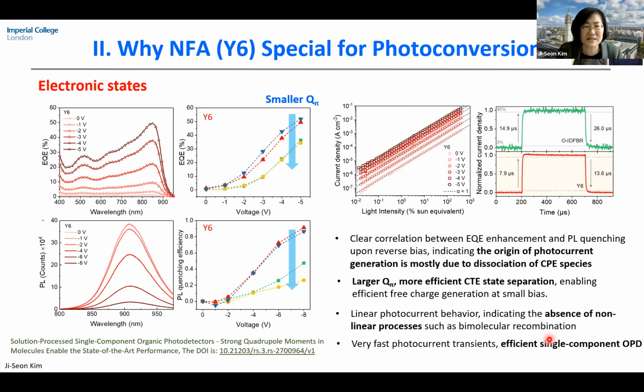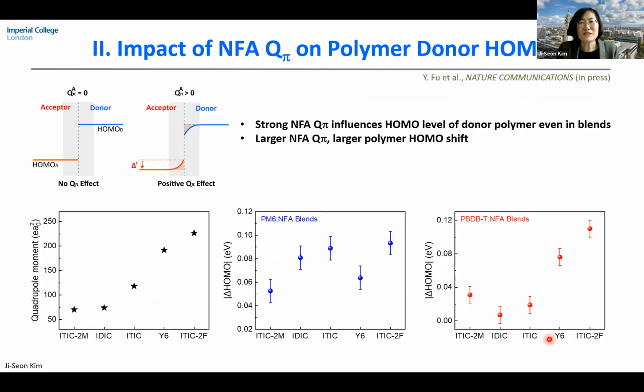organic photodetector. Okay, this electrostatic potential will impact not only the energetics of NFA. When you make either bilayers or bulk heterojunction, it will also impact the donor counterpart in terms of its energetics, as I explained, because of band bending. And we showed experimentally the energy level shift of a homopolymer when you blend this homopolymer with different NFAs with a different